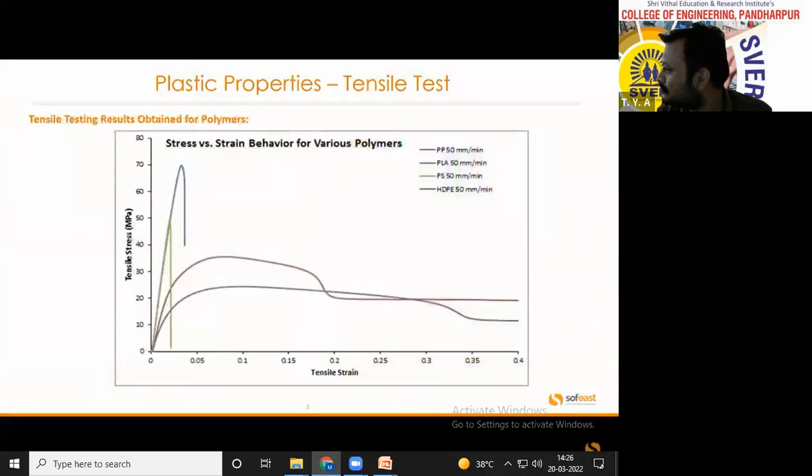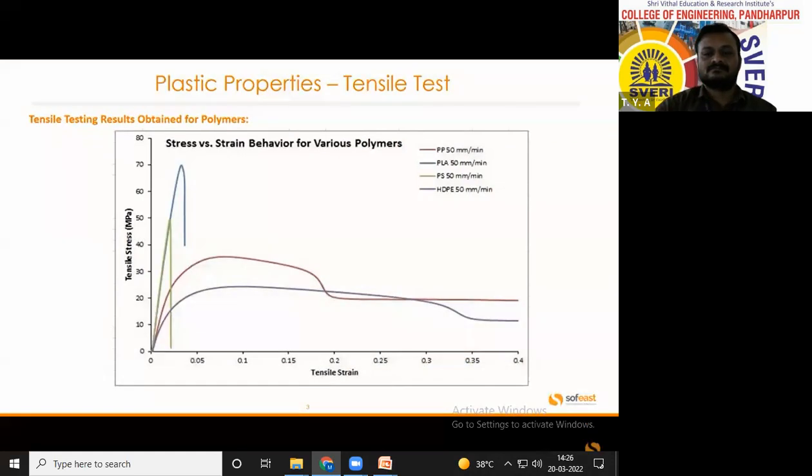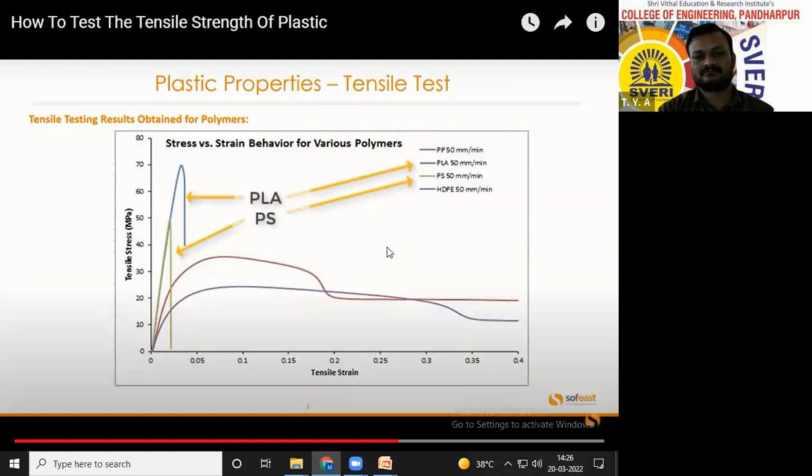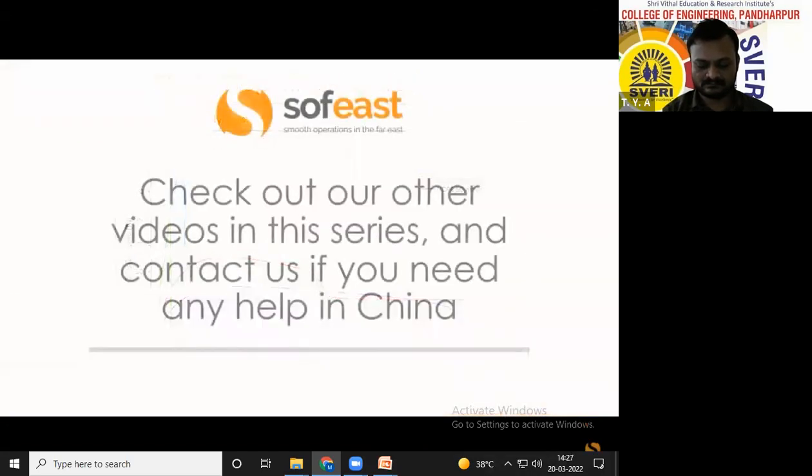So here we have a typical graph for tensile testing results. This graph is showing 4 different polymers. Each of these polymers was tested at a separation speed of 50 millimeters per minute. We can see on the left-hand side, the 2 polymers ruptured fairly quickly, but also had a high tensile stress, whereas HDPE and PP had greater elongation properties, but lower tensile stress properties. So don't forget to